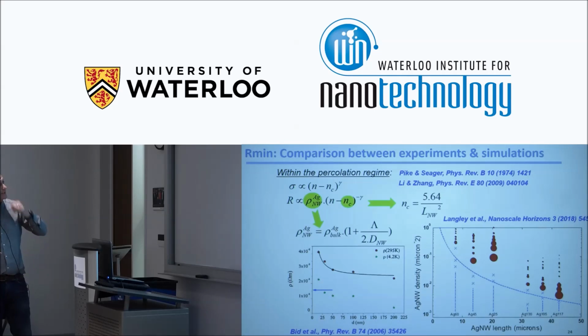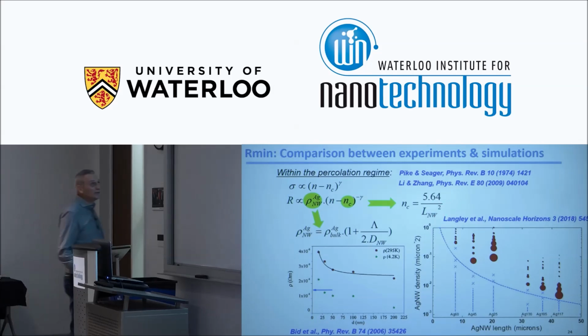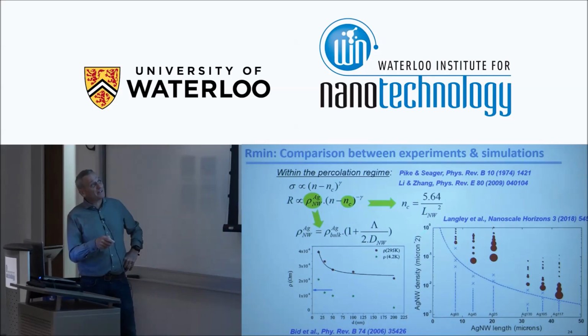Now we can also see the influence of the length. For example, we can say the resistance is proportional to the resistivity of the nanowires and (n minus nc) to the power minus gamma. I already talked about nc, which is given by 5.64 divided by the length of the nanowire squared. And so if we are, for example, plotting the nanowire density, n, number of nanowires per unit area, versus the nanowire length, this formula is given by this dashed line, blue dashed line here.